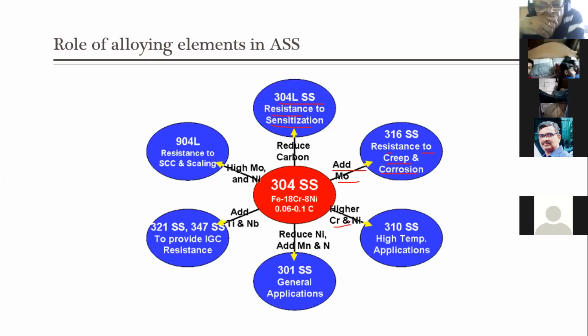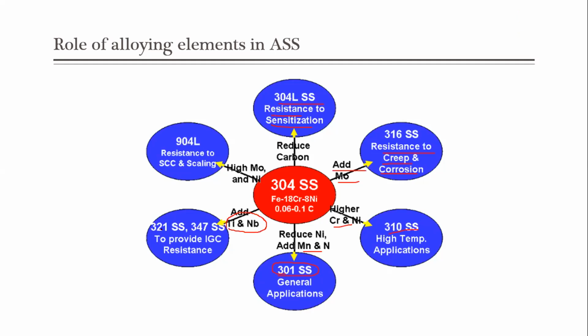And if you have higher chromium and nickel, then you get 310 SS, which has high temperature application. And if you reduce nickel and add manganese and nitrogen, then you get 301 stainless steel, which is used in general applications, and the cost of the 301 stainless steel is also very low. And if you add other alloying elements like titanium and niobium, you get 321 SS and 347 SS. It has very good intergranular corrosion resistance.